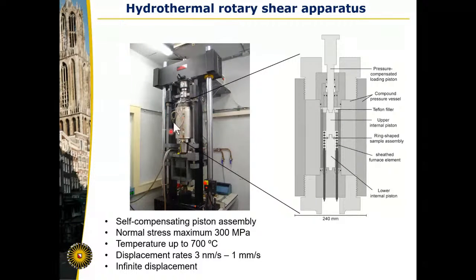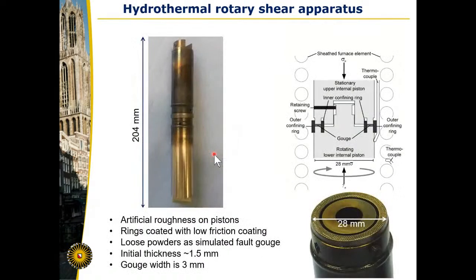In this case, the pressure vessel is filled with water, and the water is able to penetrate the sample. In this apparatus, we can reach temperatures up to 700 degrees C, and we can impose displacement rates varying between nanometers per second, which is close to the rate at which plates move, up to several millimeters per second. And because it's a rotary shear, we can keep going, in theory, for infinite displacements. So we're not limited to this 5 millimeter displacement like in the direct shear.